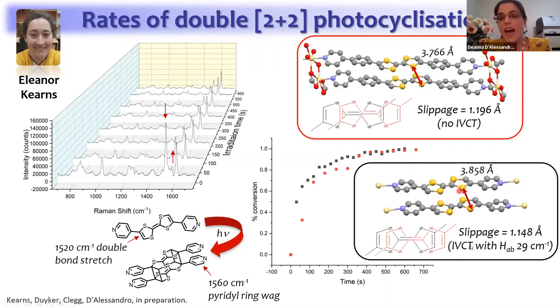And the upshot of this, in terms of the electronic properties of the system, is that for the shorter linker, we have intervalence charge transfer, but as soon as that slippage gets too large and we lose the frontier orbital overlap, we no longer have that intervalence charge transfer. So we're now really looking into this intimate connection between structure and electronic function.